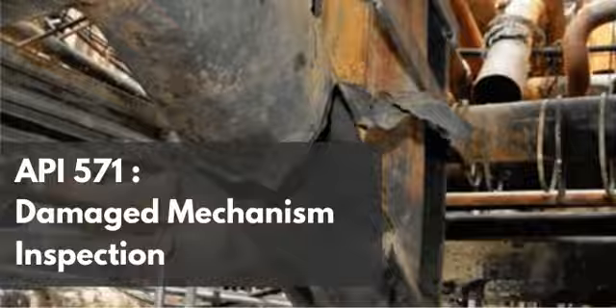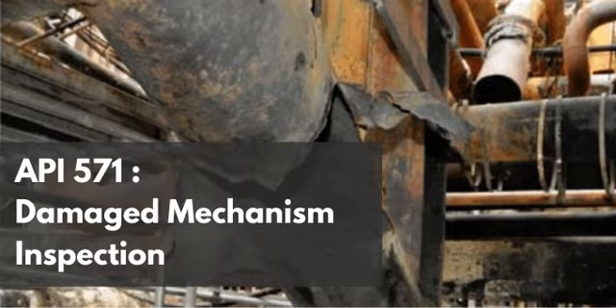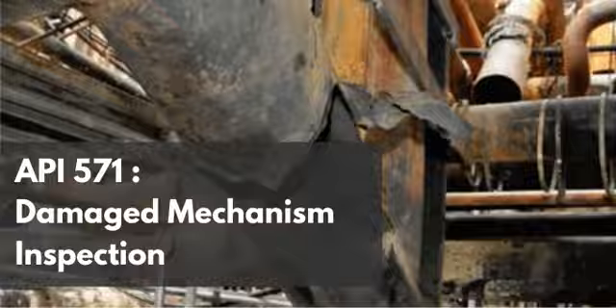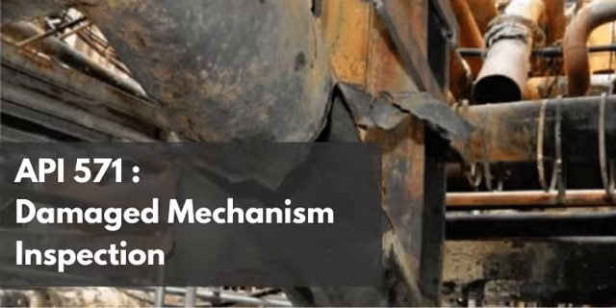If your NDT is feeding you a false positive for cracking, you are solving the wrong problem. You might shut down a multi-million-dollar operation unnecessarily to fix a crack that doesn't exist. Exactly. Or worse, while you are panicking about fracture mechanics, the real problem, which is continuous catastrophic chemical thinning caused by your operations, continues to eat the pipe because you haven't adjusted the temperature or the chemistry. That is the chilling reality check for anyone relying blindly on NDT reports without deeply understanding the morphology of the damage mechanisms at play. You have to understand what the instrument is actually seeing.